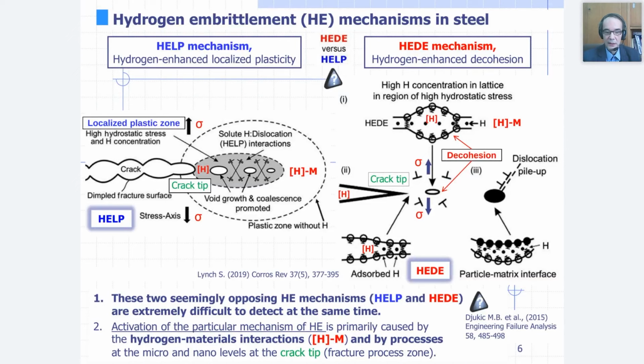Let's see the middle left picture which explains the HELP mechanism. We have a very localized plasticity zone at the crack tip because hydrogen promotes the enhanced movement of dislocations, which provokes the localized plasticity effect at the crack tip, and as a result we have void growth and coalescence, and typically due to the HELP mechanism we have a ductile failure due to the microvoid coalescence fracture mechanism. Also important is the effect of stress marked as sigma on that diagram.